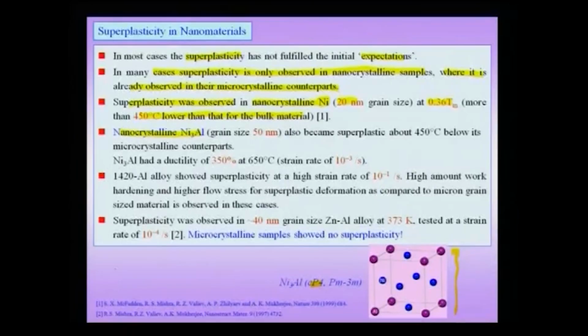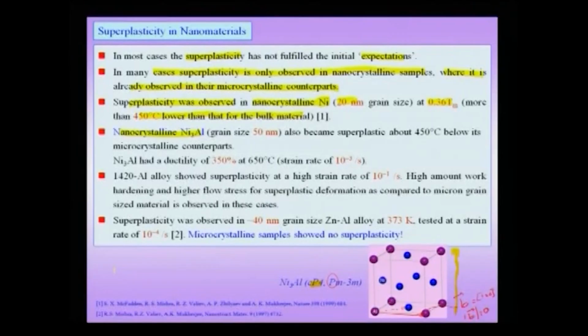Now, the fundamental lattice translation vector, because it is a primitive structure, is this, and if you had a disordered Ni3Al, it would have been this vector, which has a length of root 2 by 2 a, but in this case the Burgers vector is of the type <100>, and therefore the magnitude of the Burgers vector is equal to a. That means that the Peierls stress in such ordered structures is going to be large, and typically they would behave in a very brittle fashion with very low tensile ductility at room temperature. So, if you observe superplasticity in these cases, it is actually very surprising, and the 50 nanometer grain size nanocrystalline Ni3Al became superplastic 450 degrees below its microcrystalline counterparts. So, this is again very beneficial.